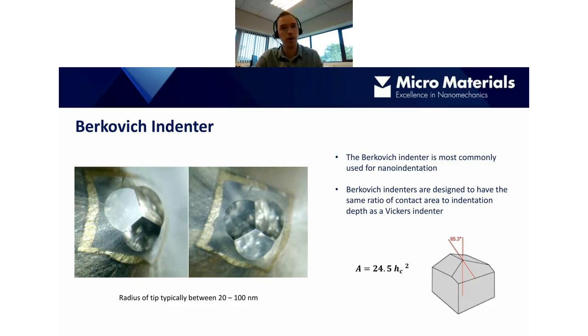If you have a three-sided pyramid, it's hard to get the tip of the indenter very sharp, which is of course very important for nanoindentation testing because some of the indentation depths are very, very small. So the precise geometry of the tip is very important in order to get accurate mechanical property measurements. Of course, it's not infinitely sharp, not perfectly sharp at the very tip of the indenter. What we usually see is that the tip is effectively like a small sphere of radius typically between 20 and 100 nanometers. If it's a brand new indenter, it may be around 20 to 40 nanometers. Over time, that tip will start to round and the effective radius will increase.